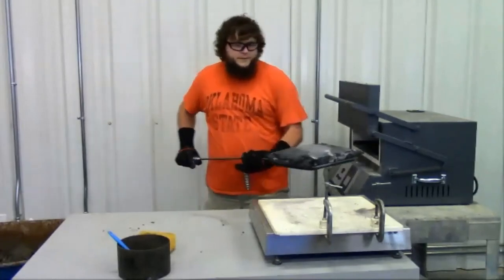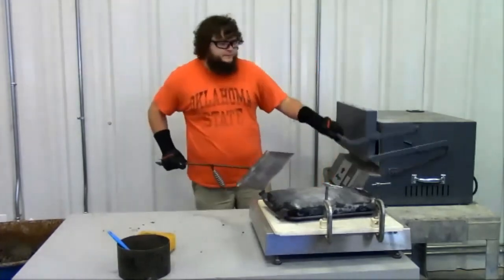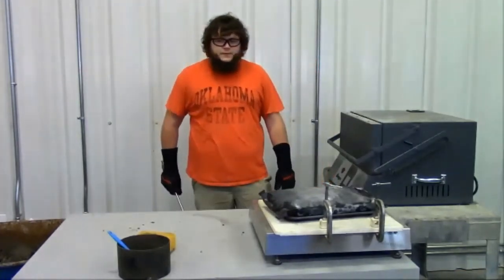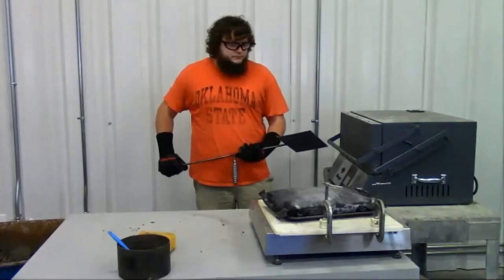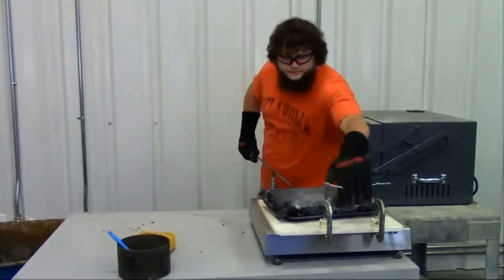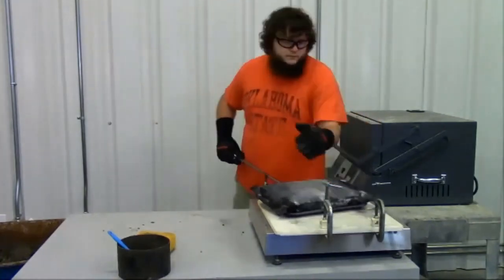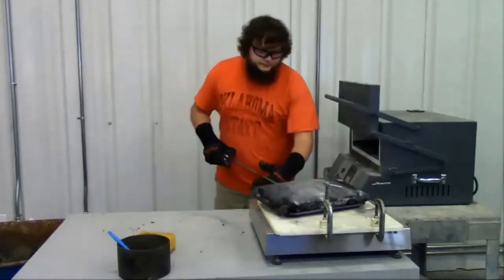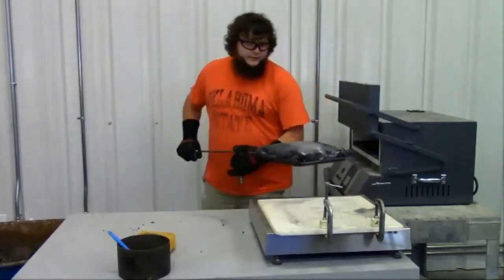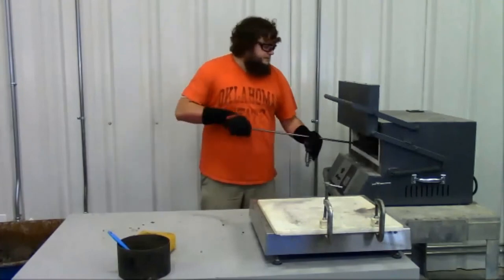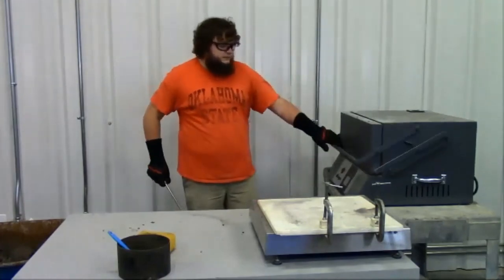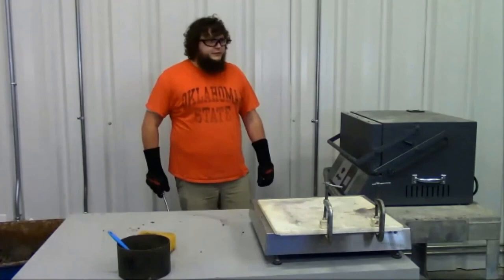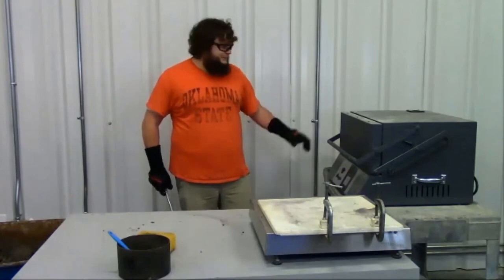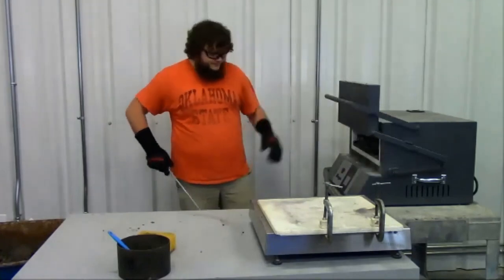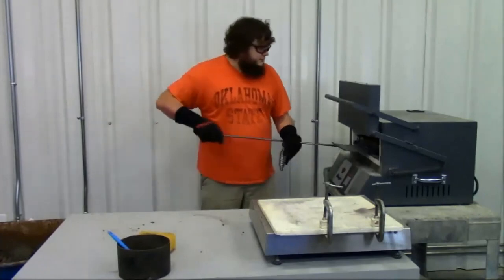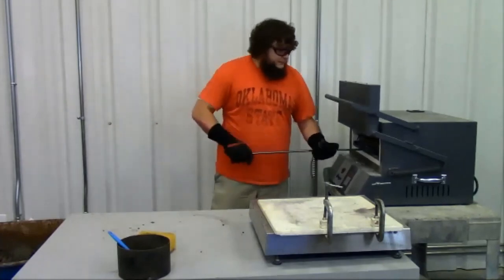remove the concrete sample and place back on the scale. Note the insulating material between the platform stage of the scale and the pan itself. Record that weight and put the sample back into the kiln for an additional 2 minutes. After the 2 minutes has passed, remove the sample and weigh again.